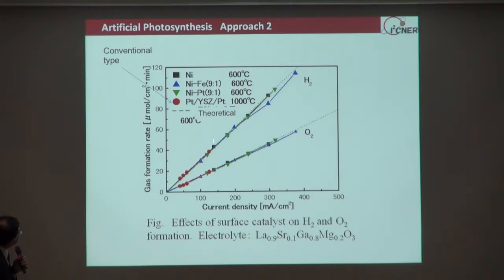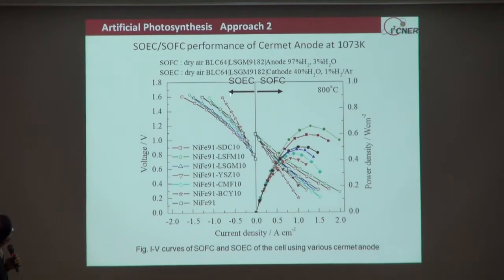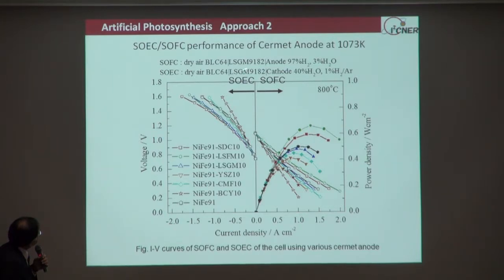by the same cells. Therefore, by decreasing the temperature, we also observe much improved stability of the cells. And then this is reversible operation. For example, the solid oxide electrolysis cells generated hydrogen, and then the obtained hydrogen can be converted to electricity for the reversible operation of these cells. As you can see here, compared to the simple nickel iron anode, by combination with the lanthanum strontium iron manganese, we observe reasonably large current densities and also reasonable power densities. The cell is reversibly operated.